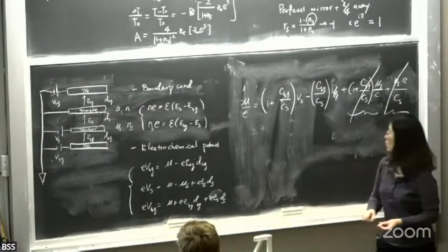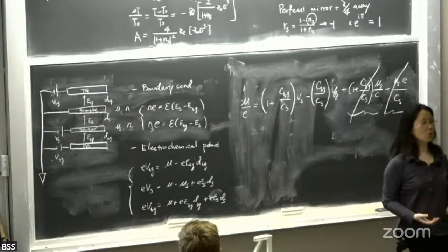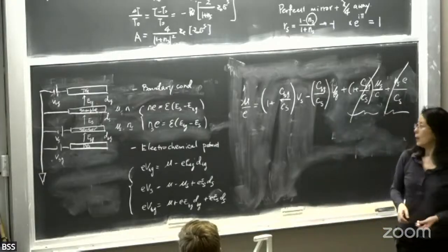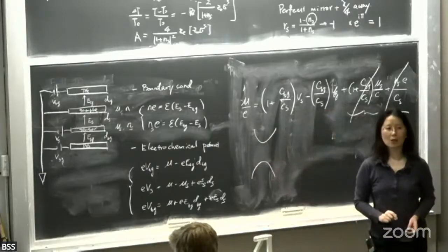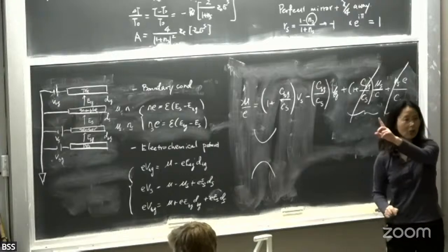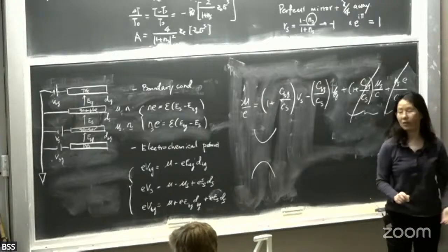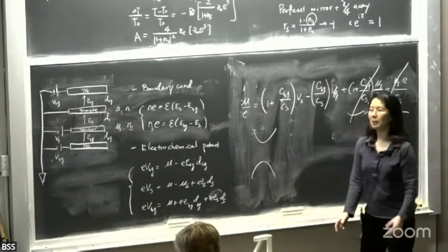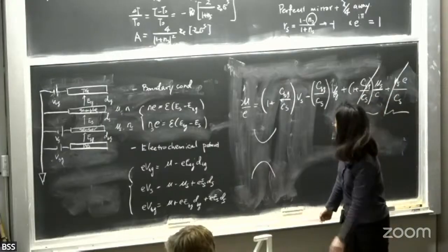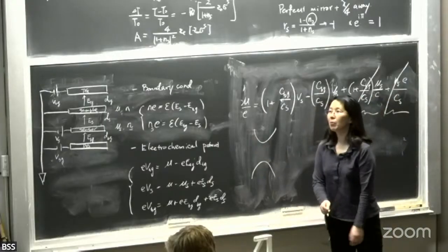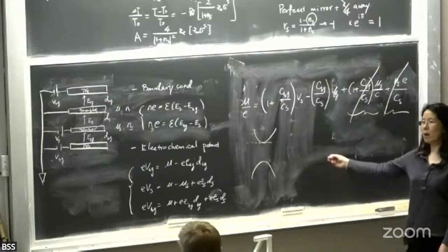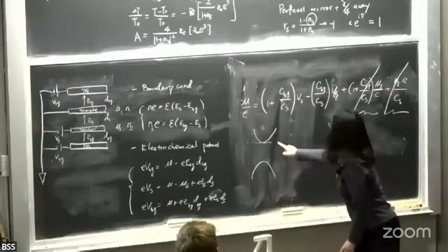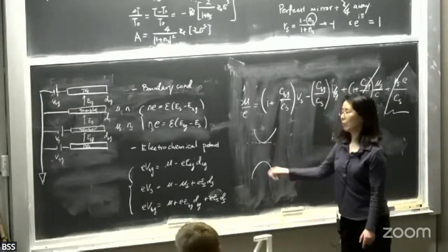So the question is, what kind of reference point can we use for a monolayer of semiconductor? We already saw it has a very large response when you have some kind of band-to-band transition. So a very convenient set point will be right at the bottom of one of the bands, conduction band bottom, for example.